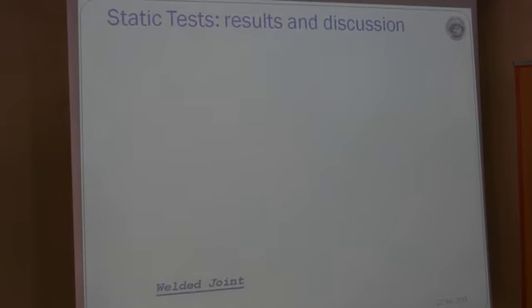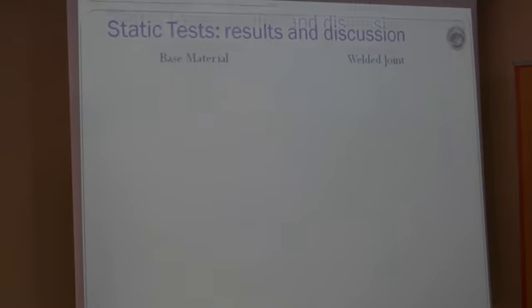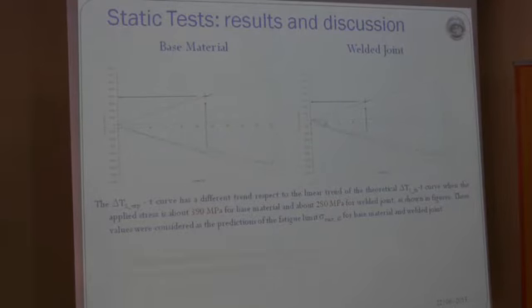In this slide, you can see the stress in time and the surface temperature rise for the base material. We can see there is a deviation from the linearity of the thermoelastic effect at a stress of 390 megapascal. If we look at the welded joints, it is the same, but of course we have a different stress, 250. After, the fatigue limit prediction for the base material was confirmed by the fatigue test carried out at 420 megapascal, which did not produce any failure after 2 million cycles.